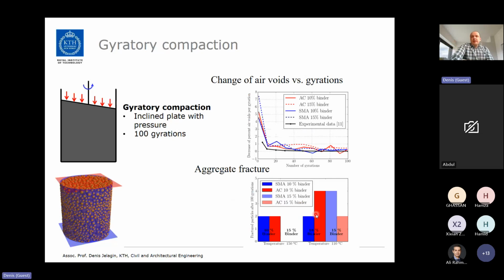We also looked at gyratory compaction, where we looked at air void evolution during the compaction process. Again, the black line comes from experiments, and the colorful lines are asphalt concrete and SMA obtained at different binder contents, etc. And the discrete element model also allows us to gain insight into aggregate breakage during the compaction process. Not too much aggregate breakage happens during those gyratory compaction simulations, as those loading scenarios are designed not to break aggregates excessively, so that's expectable.